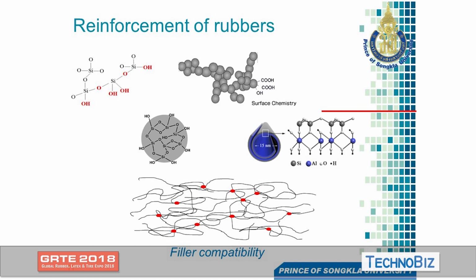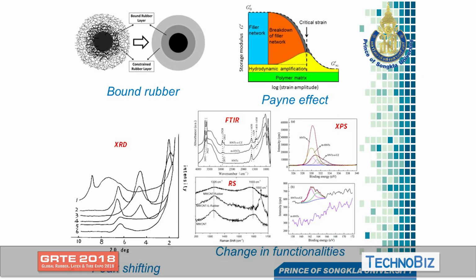And last but not least is the compatibility between fillers and polymer matrix. As you can see here, each type of filler has its own surface chemistry. So we have to look at whether the surface chemistry of the fillers and the rubbers is compatible together or not. Then we can observe later whether the properties are enhanced. Here is the example of the surface chemistry on the fillers, for example HNT, in my case, carbon black, silica, and so on.